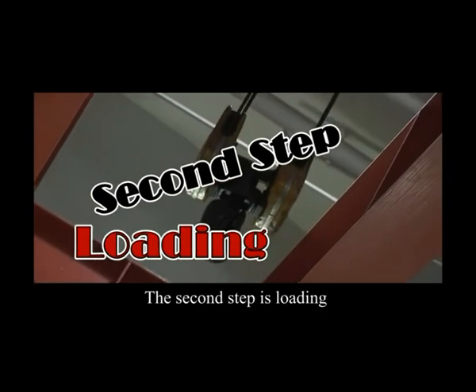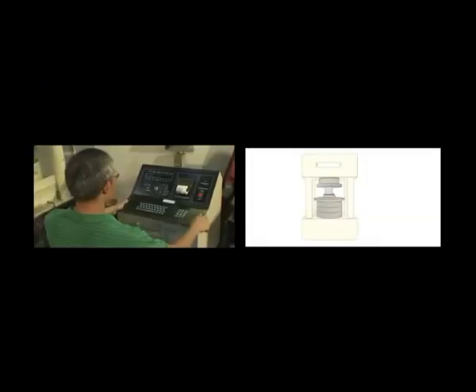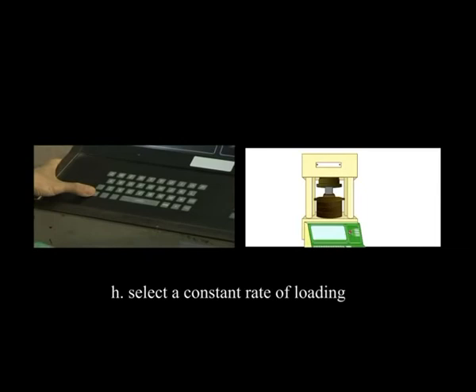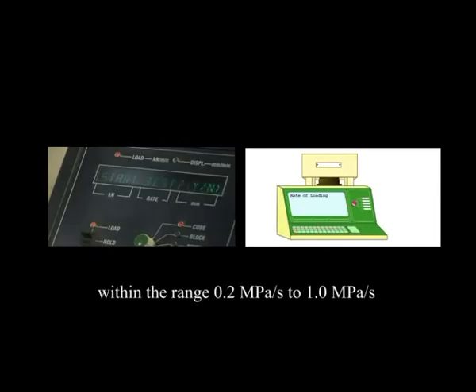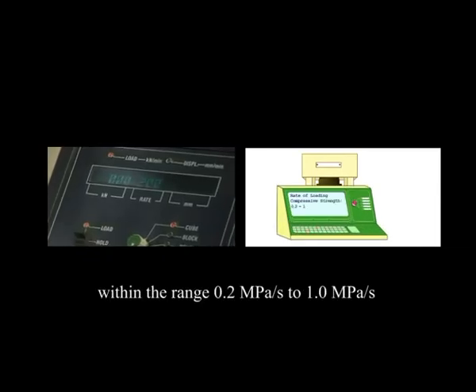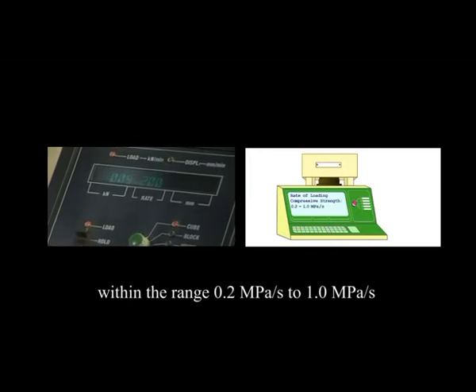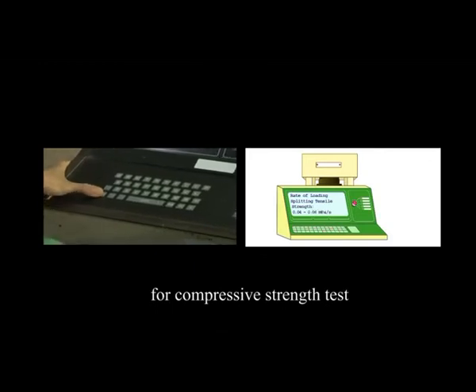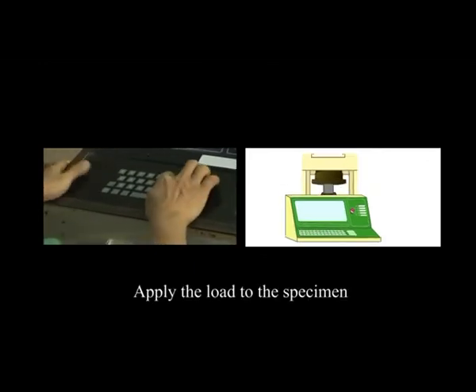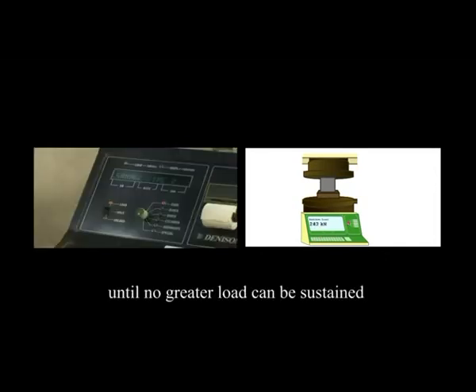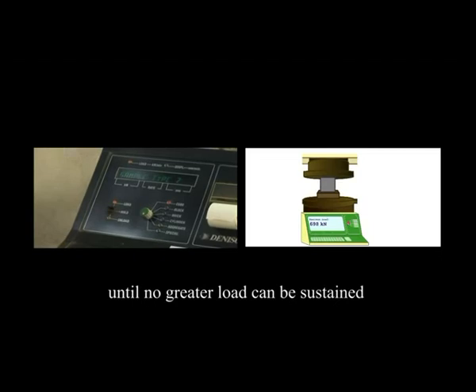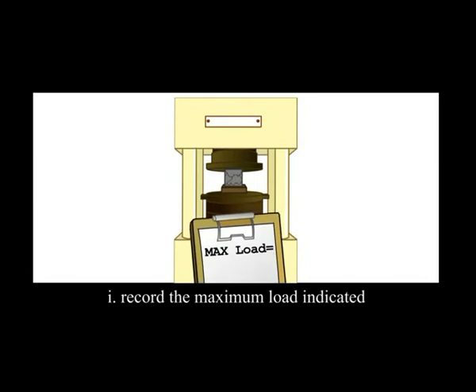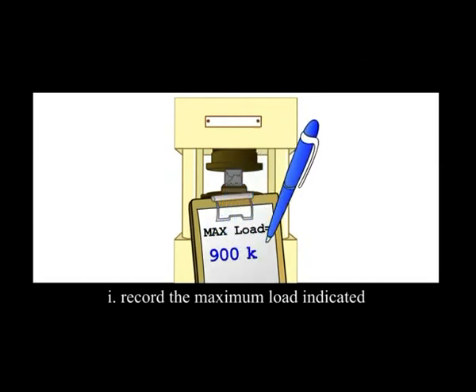2. The second step is loading. H. Select a constant rate of loading within the range 0.2 megapascals per second to 1 megapascal per second for compressive strength test. Apply the load to the specimen without shock and increase continuously until no greater load can be sustained. I. Record the maximum load indicated.